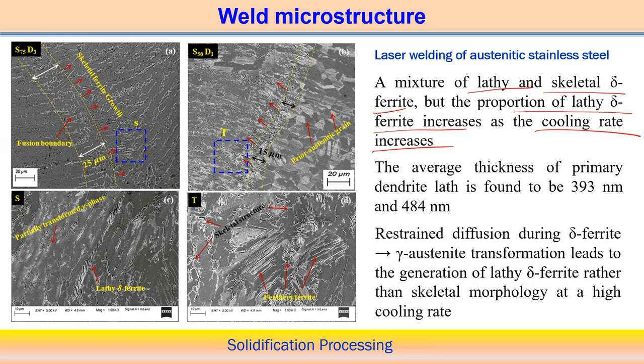But he also measured the thickness of the primary dendrite lath thickness, which was found to be between around 393 nanometer and 484 nanometer. So in that range we can get the average thickness of the primary dendrite lath thickness. You can also measure the dendritic arm size, which can be different depending upon the cooling rate during this process. Finally, we can observe that restrained diffusion occurs during the delta ferrite to gamma austenitic transformation, and that actually influences the generation of the delta ferrite.